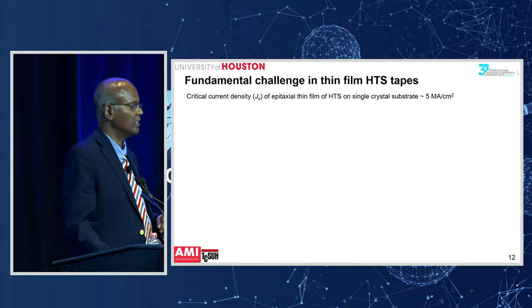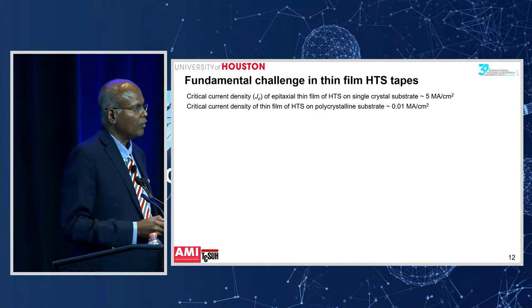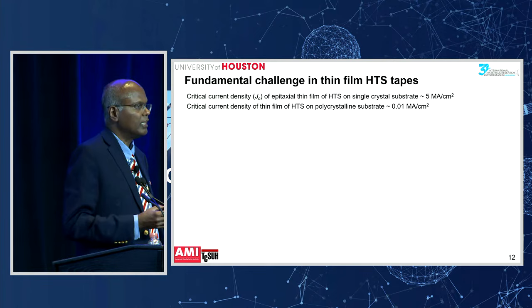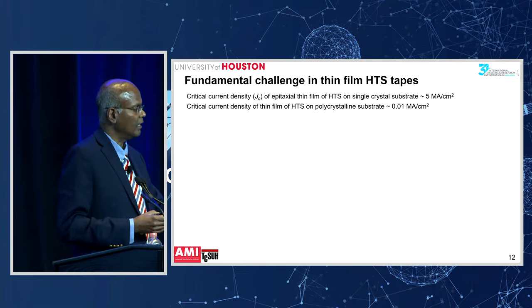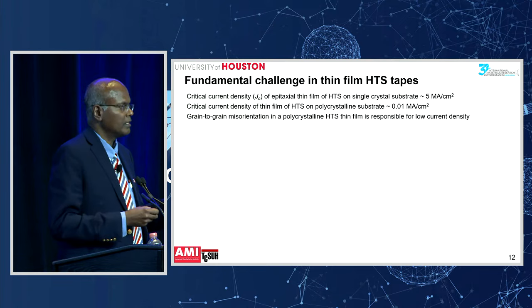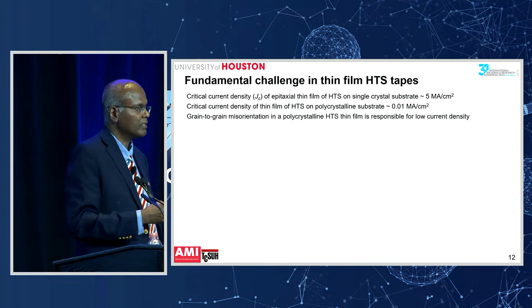But that's only if you grow the superconducting film on a single crystal substrate. If you grow the same superconducting film on a polycrystalline substrate, you can only carry about 10,000 amperes per square centimeter, about 500 times less current than growing on a single crystal substrate. The reason for this is the grain-to-grain misorientation. If you grow it on a polycrystalline substrate, obviously you have grain boundaries, and those grain boundaries are an impediment to the flow of current.